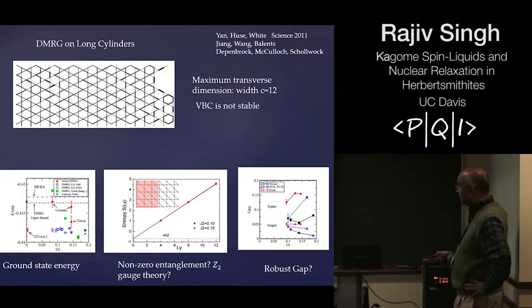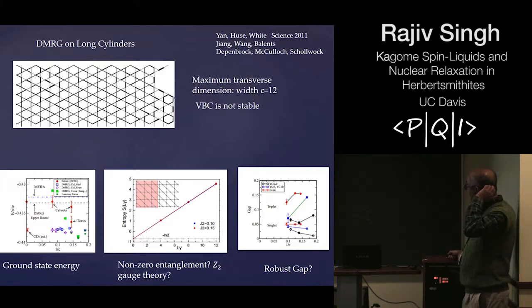and they can get an energy which is much lower than what we were getting from these different perturbation theories around different valence bond configurations, giving us evidence that there is an extra lowering of energy due to the resonance. There is also a calculation of entanglement entropy by this group of Leon Balents and collaborators, arguing that there is a topological entanglement entropy which corresponds to that of a Z2 spin liquid. And there is also the claim that somehow this very large number of singlet states and the difference between the singlet and the triplet gap is not really visible in the DMRG studies. It tends to show that with increasing size, basically the singlet and triplet gaps become comparable.